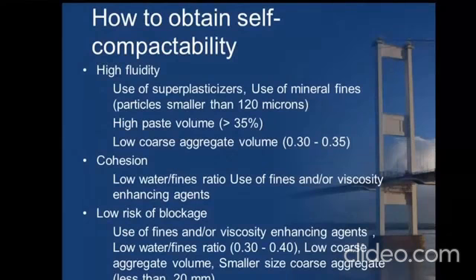So if you see the customization mix proportion of self-compacting concrete, it is actually very different. The paste volume is a very major factor here, and we have a very low aggregate volume here, only 0.3 to 0.35. And next one, as I told you, we need a viscosity modifying agent, VMA, in order to look after the flowability of the concrete.